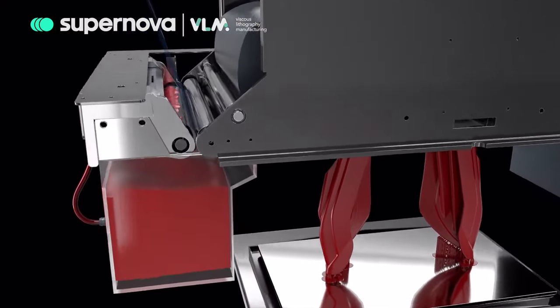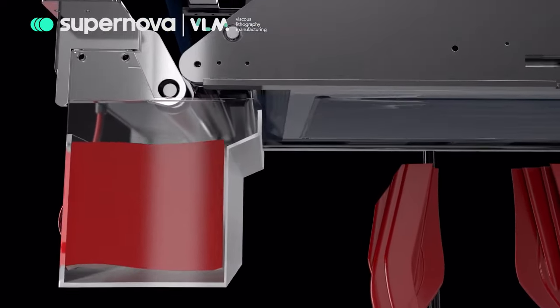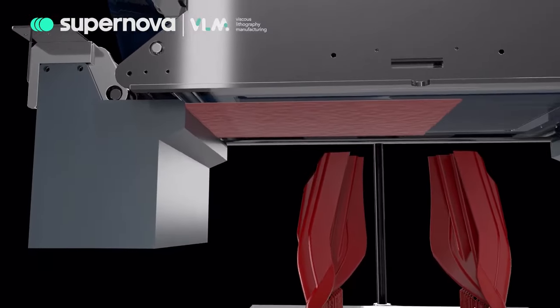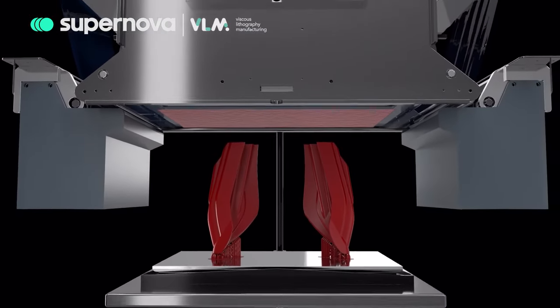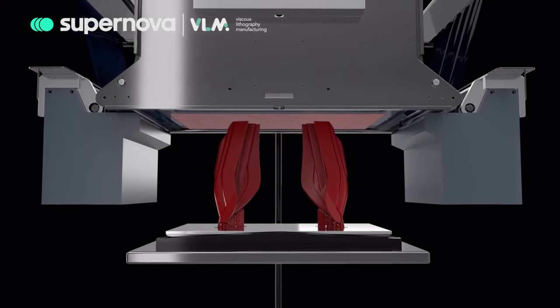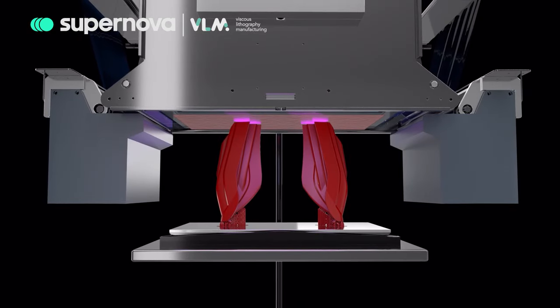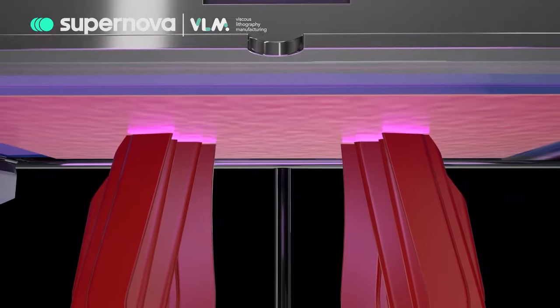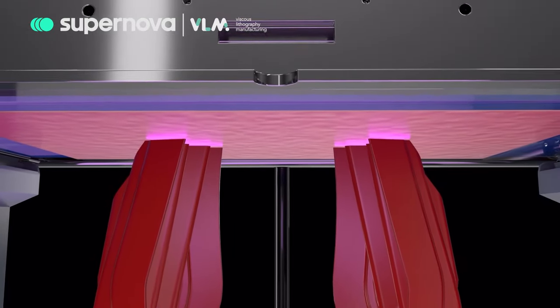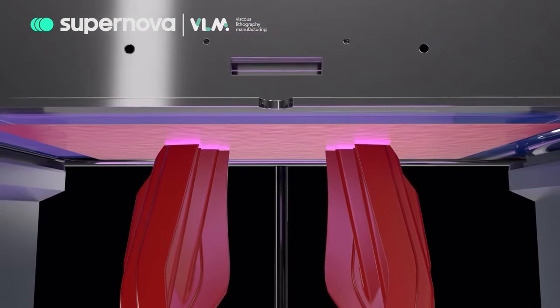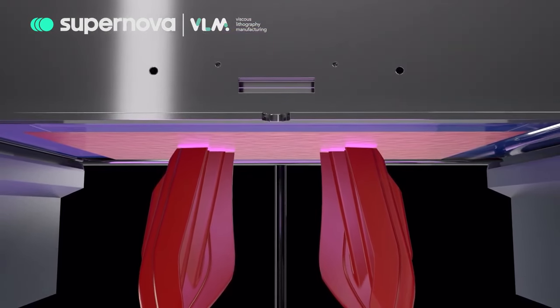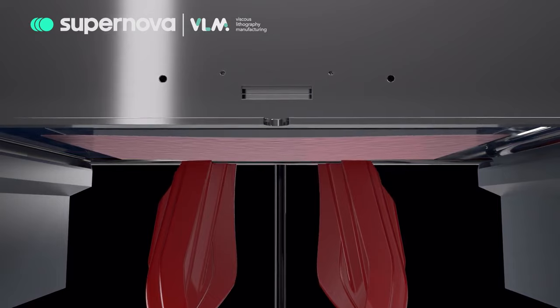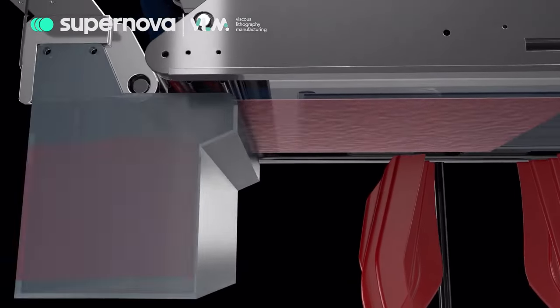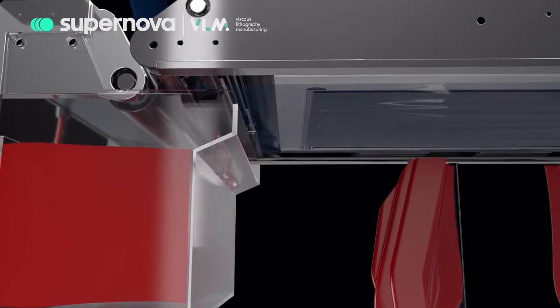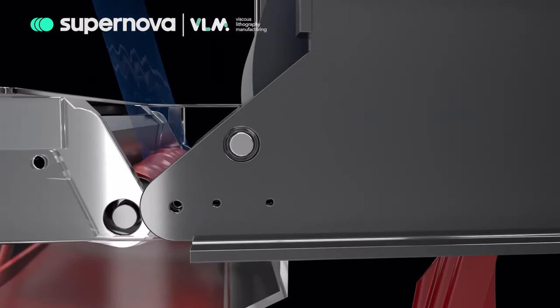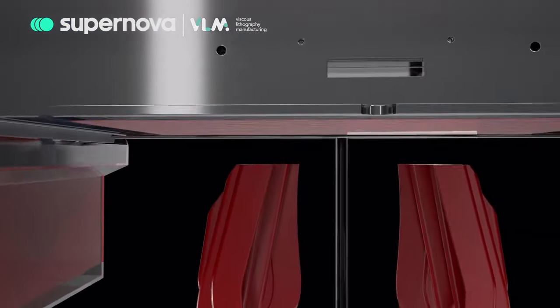To do so, the resin is first picked up by a roller from the material bucket and accurately laminated to the underside of a transparent film, which is then transferred to the curing area. The build plate rises to come into contact with the recently laminated resin at the desired layer thickness. The UV light engine cures the resin solely in the specified area, creating a new layer of the object to be printed. The build plate then retreats, causing the recently cured layer to peel away from the film, while the uncured resin is recovered and recirculated up to the material bucket. This process is then repeated until the print job is complete.